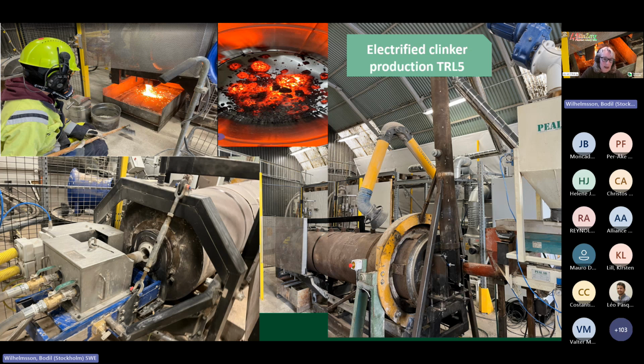We fed the kiln with approximately 80 kilograms per hour. We achieved a 70% CO2 atmosphere, which is a bit lower than we wanted. We want, of course, to increase it to more than 95%, because that will be the best option for the gas cleaning, the next steps. But here you also see the product when it comes out from the kiln, and here it's shown in a bucket. During the test we did advanced characterization of the heat transfer along the kiln, inside the kiln, and the kiln lining. We measured heat flux and intensity and temperatures, of course, and we also measured the flue gas composition and put a lot of effort into characterizing the material.